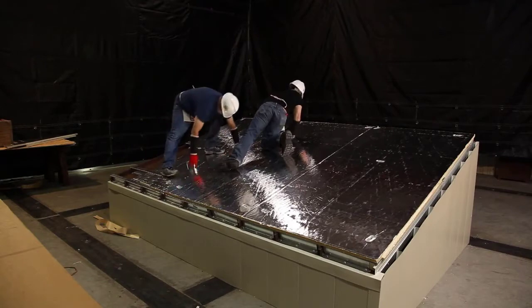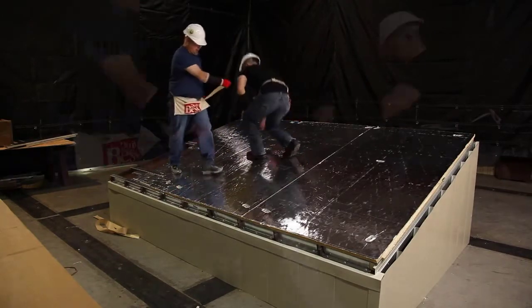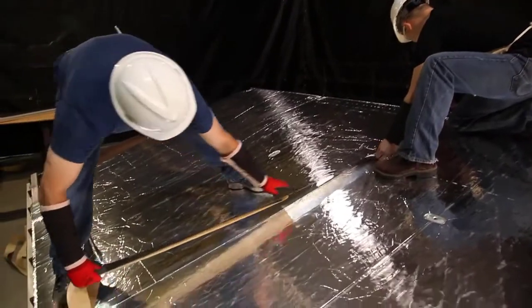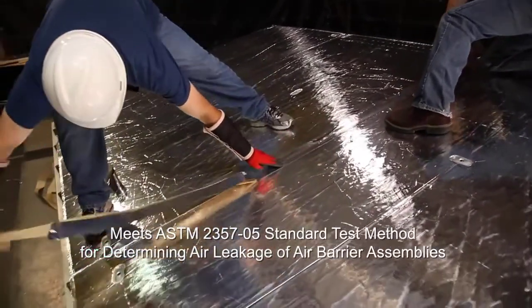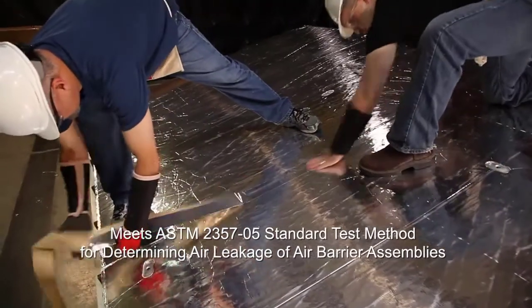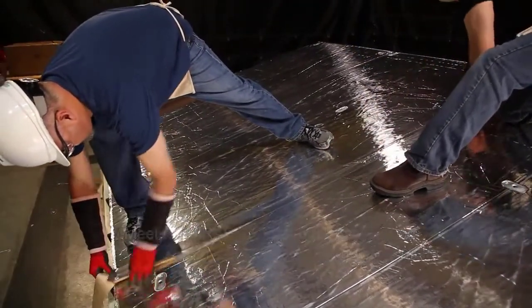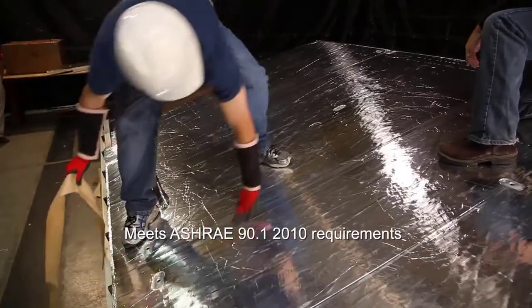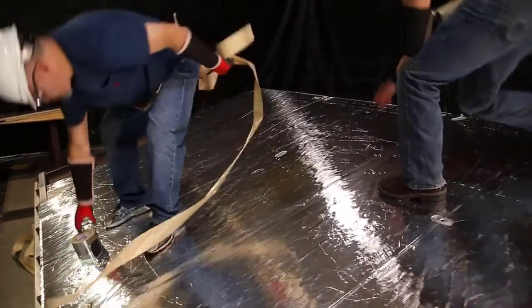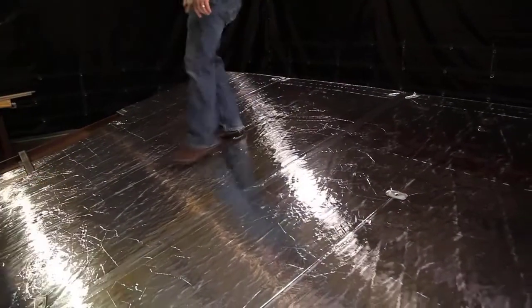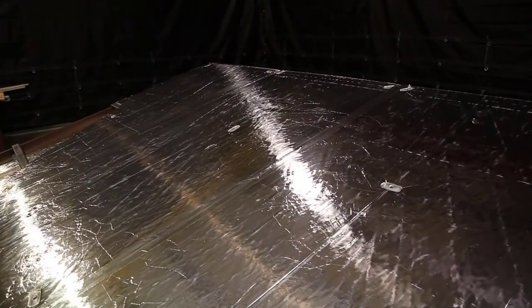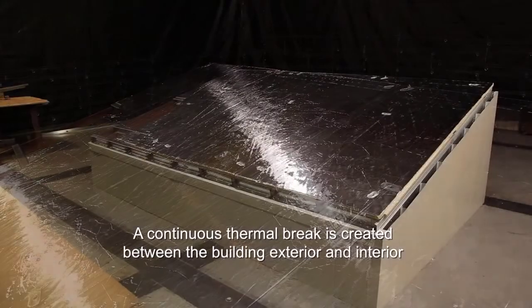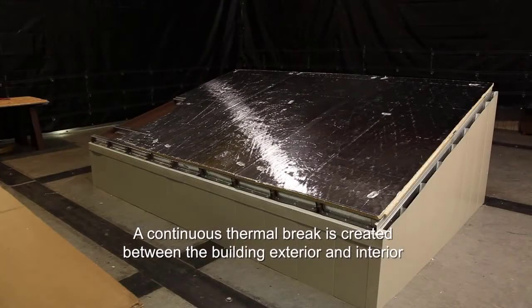When used in conjunction with the appropriate joint closure system, polyisocyanurate insulation effectively blocks airflow, meeting ASTM E2357-05 standard test method for determining air leakage of air barrier assemblies and ASHRAE 90.1 2010 requirements. And the low perm rating helps to reduce moisture condensation within and below the insulation. Also, the insulation, especially if it's taped, can provide a second layer of defense against any leaks in small gaps or holes from wind-driven rain. Note that the second layer of insulation covers the top of the structural sub-purlin, creating a full thermal break between the building exterior and interior.